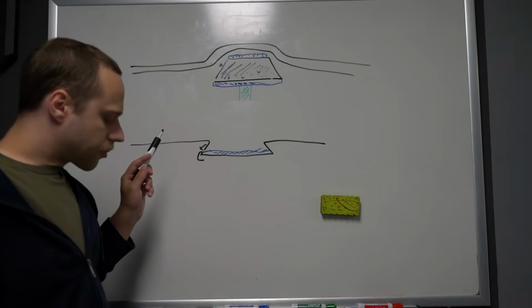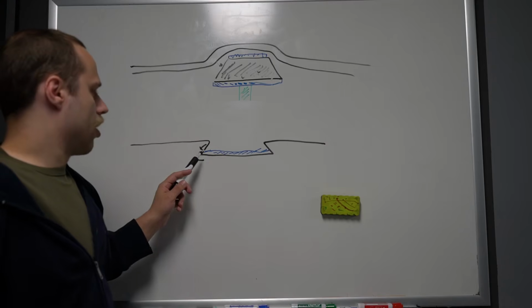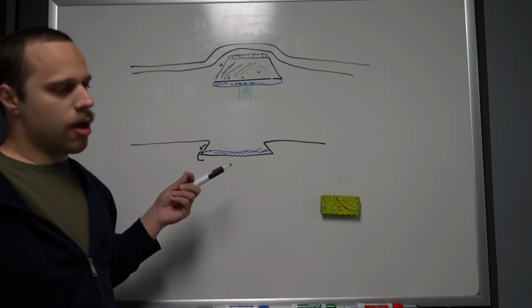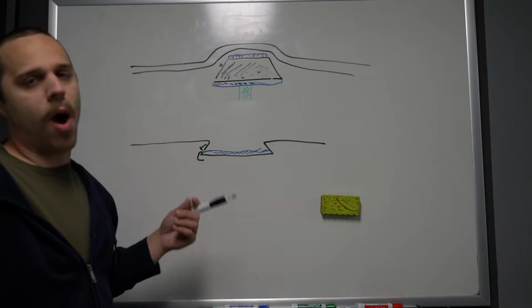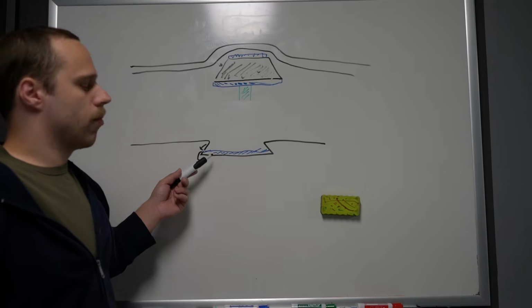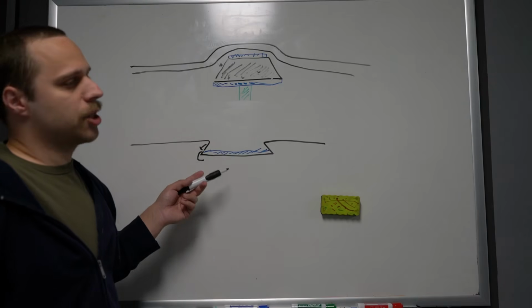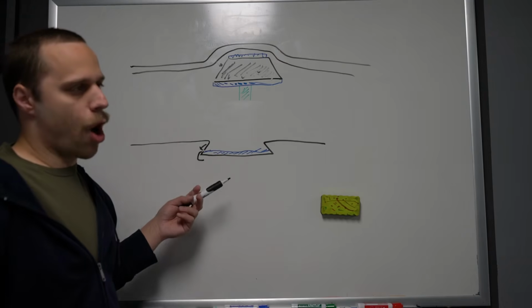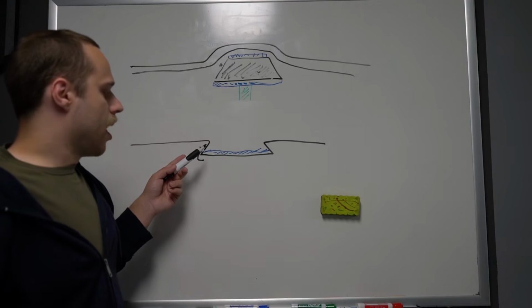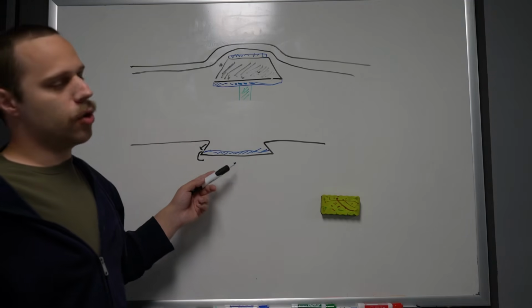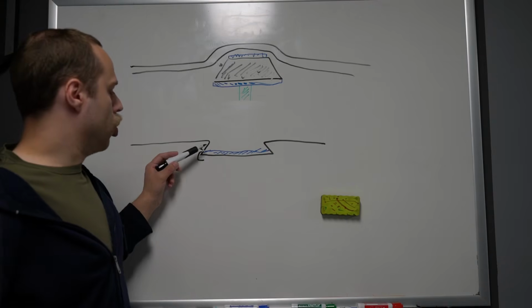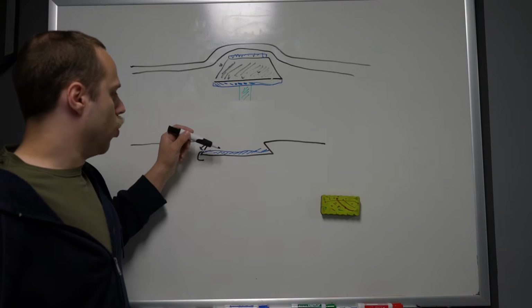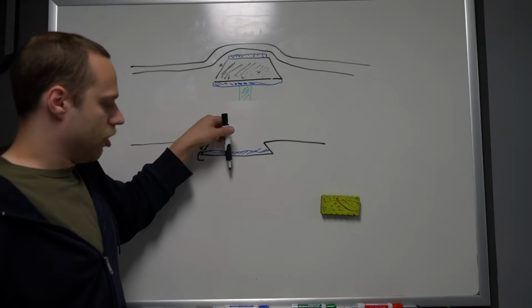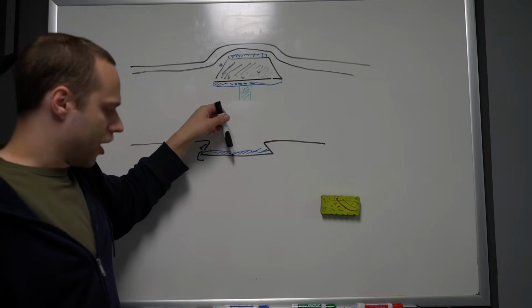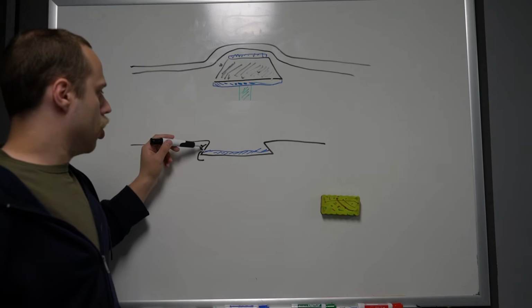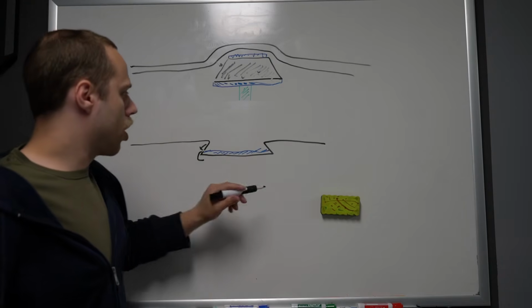And so part of the art here is that there are various techniques you can use with sonication and just swabbing the surface of the die and so on to remove loosely attached materials that have either completely floated off or are beginning to delaminate. And so figuring out exactly when to use some of these more aggressive techniques to remove the titanium nitride, which will enable etching in the direct downward direction, as opposed to allowing it to be undercut,